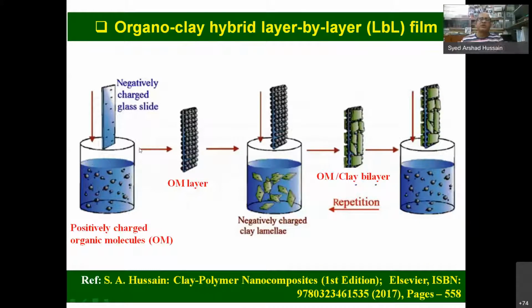And we also prepare layer by layer self-assembled films. This is through electrostatic interactions. We use dispersions of clay here. Then we dip a charged substrate, and of course the materials are oppositely charged. Then they will interact here, and you see organic materials attached here. Then we dip in the clay, and alternately it's a clay-organic system. So it's a self-assembled system, layer by layer depositions.